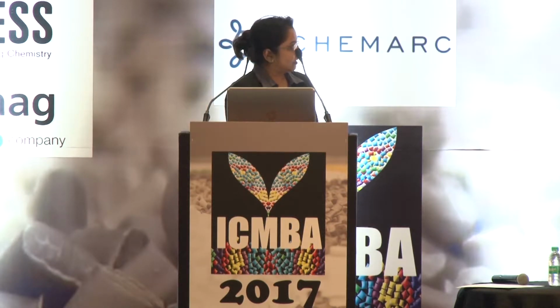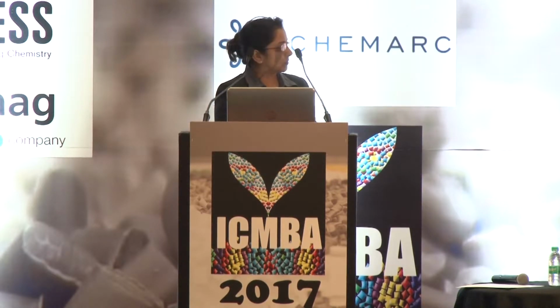And if you see here, this is the color retention. This is 10 micron thickness. The standard, 8% replaced, and 12% replaced. And this is 25 microns thickness. And again, the same sequence of replacement, standard, 8%, 12%. And this is 50 microns. You can see the color is retained more or less, almost comparable everywhere.